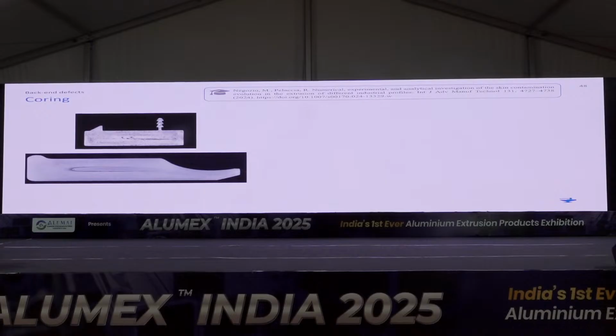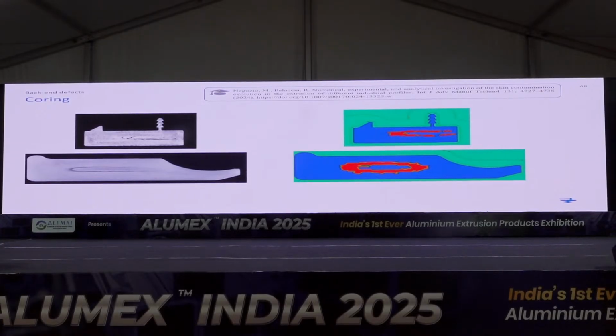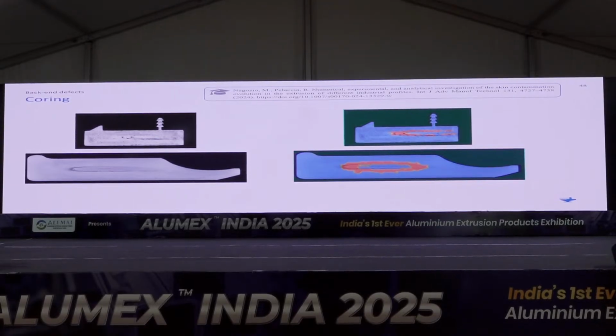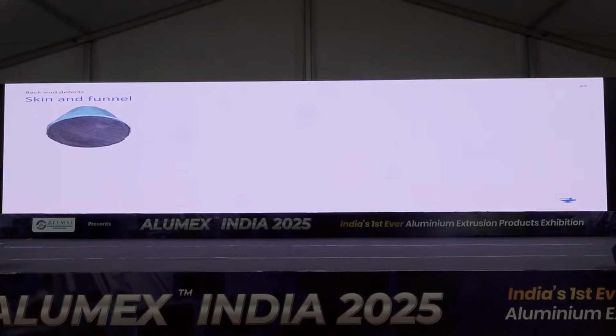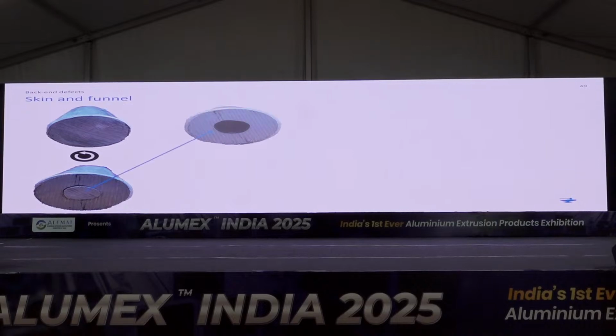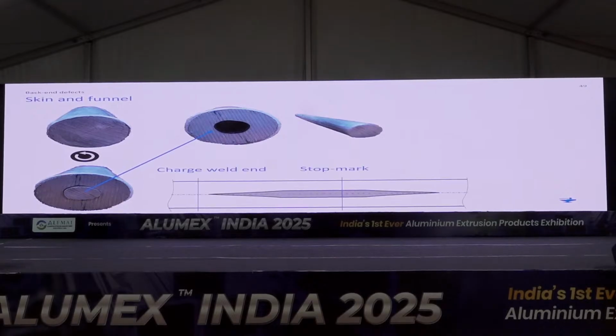There are some examples from some of our colleagues from Italy, from researchers and scientists. So this is a so-called coring defect, which you can see here, which correlates well with this data. A very simple example of rod extrusion. If we rotate this rod, we can see that some part of this profile is separated from each other and can even be extracted from it. If we look at the extrusion in a section, we can find this internal, let's say, cylinder of scrap inside, and we can also predict it using a simulation.